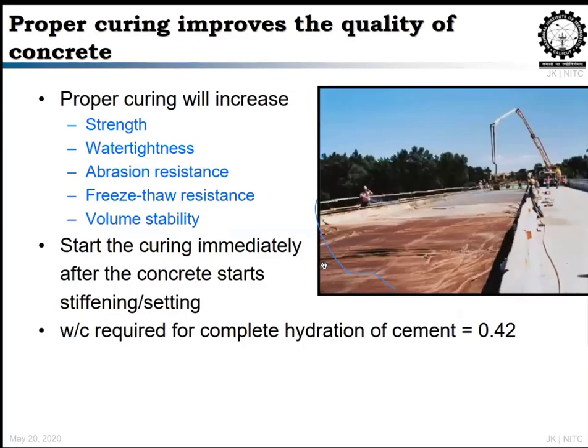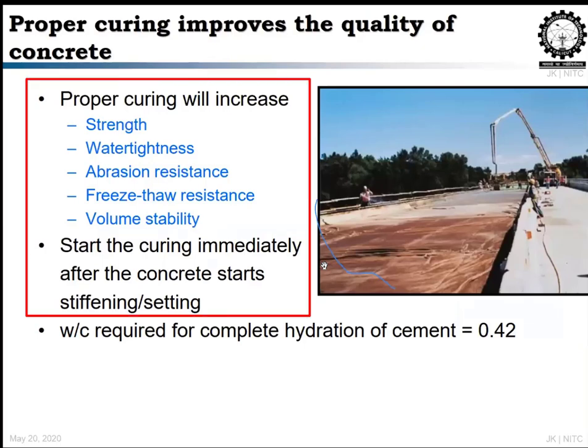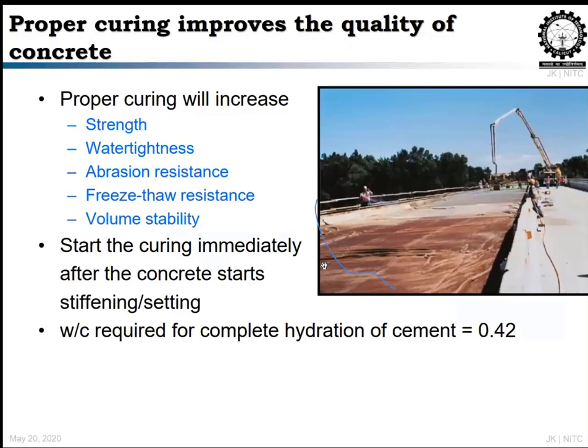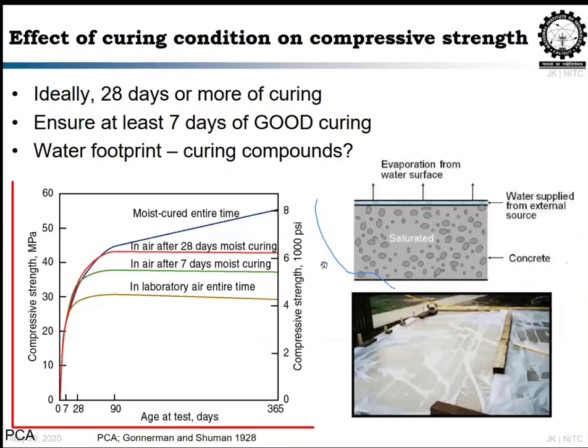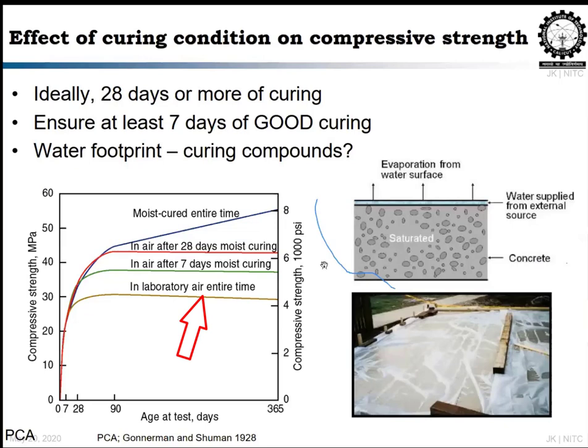Okay? And even if you have a good quality concrete which is made, concreting is done, curing is very important. Obviously it will give strength and water tightness and abrasion and freeze thaw and volume stability. But how long we have to cure, and how to see the importance or influence of proper curing. So you see a graph which shows the compressive strength with respect to the age. There we have taken 4 cases where the light brown color is the case where it is cured at the laboratory, not with water, only with air. We didn't expose it to any ponding or moist curing.